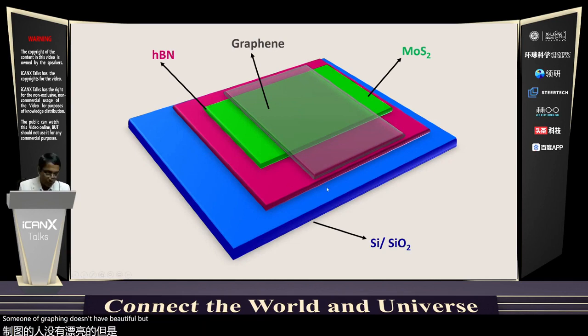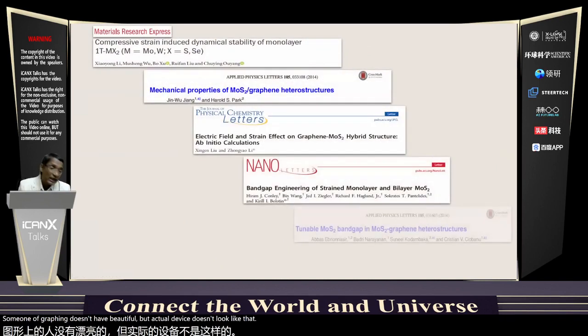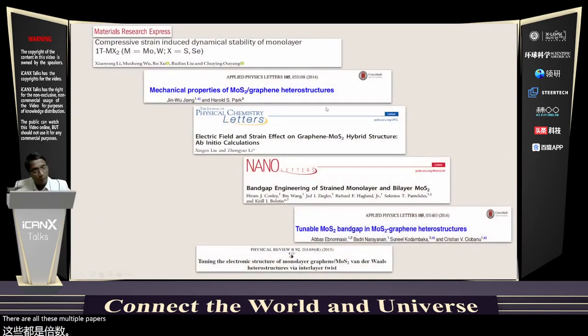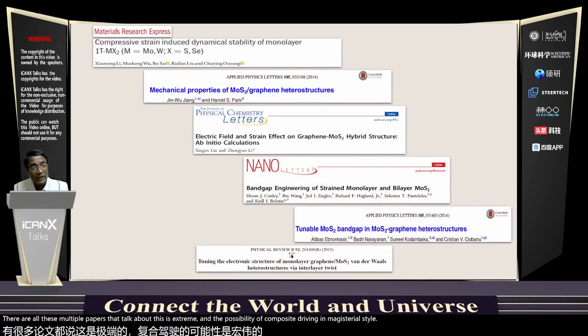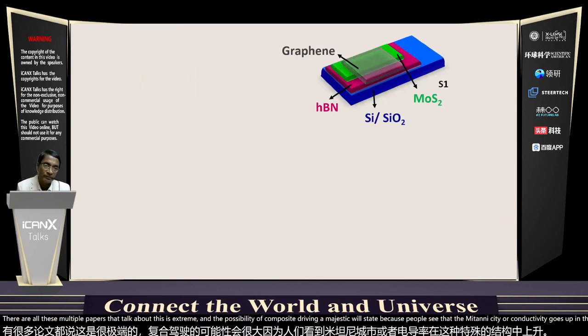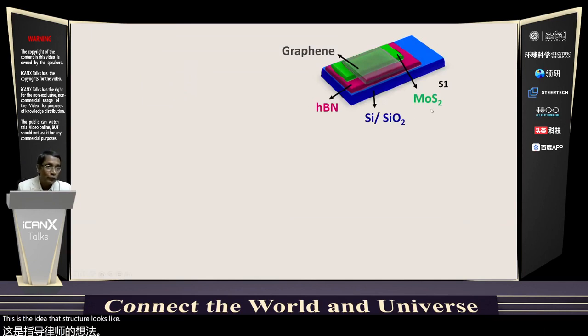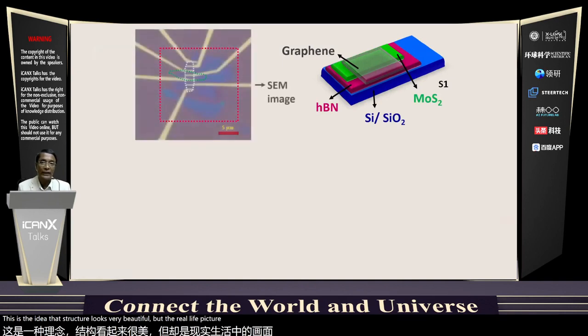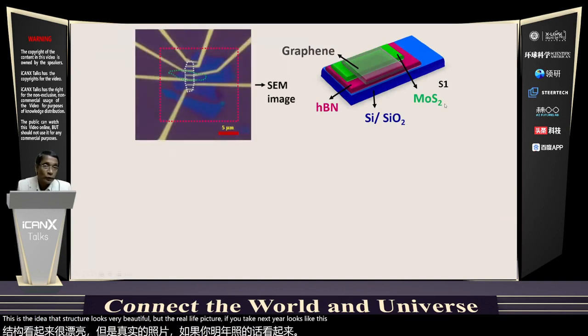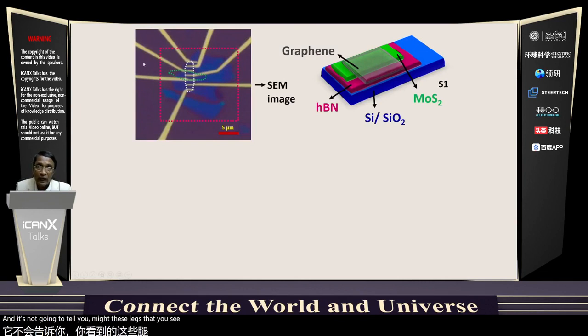Beautiful, but actual device doesn't look like that. There are multiple papers that talk about this compressive strain and the possibility of compressive strain driving a metastable state, because people see that the metallicity or conductivity goes up in this particular configuration. This is the idealized structure. Looks very beautiful, but the real life picture, if you take an SEM, looks like this. And it's not going to tell you much. These legs that you see are all the leads of the device to measure its transport properties, and you hardly see anything. And these are the wishful thinking of where the MoS2 can be placed.